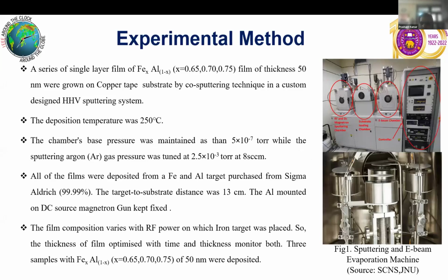We have fabricated the FeAl through co-sputtering, on which this is our system. We deposited through co-sputtering, in which the power of the aluminum gun was fixed, and the power of the iron gun varied the composition of FeAl. We have basically made three compositions: Fe65 Al35, Fe70 Al30, and Fe75 Al25.